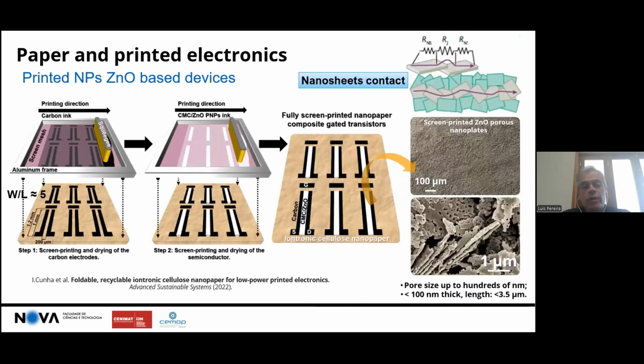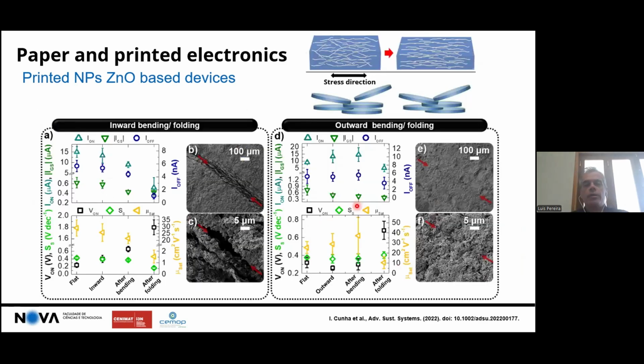And to try to minimize it, we went for an approach where the ink, instead of being made of spherical zinc oxide nanoparticles, uses nanoplates of zinc oxide. And so basically, during printing, they tend to assemble over each other. Again, we have the problem of the contact between the nanoplates, so everything will be determined by the contact to ensure the percolation. But as they assemble over each other, even when they are submitted to a stress, so when you bend, you are basically putting a tensile stress on the surface of the substrate. When you bend inwards, you put a compressive stress. When you bend outwards, you put a tensile stress.